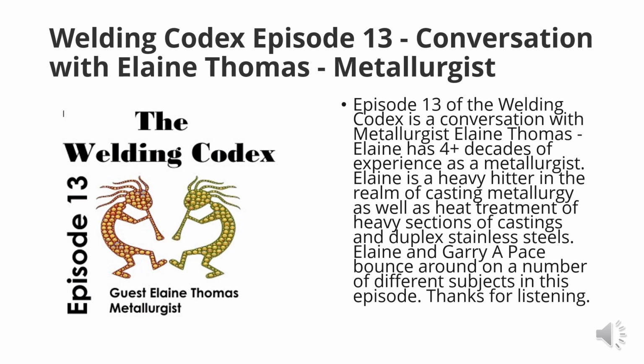I've been involved with ASTM, American Society for Testing Materials, and the specifications that deal with duplex just exploded with different alloys during the 80s. One of the ones I had a hand in helping to develop was the ASTM A890 grade 5A. That's sort of the general spec. The pressure vessel spec is ASTM A995 grade 5A. Those are called super duplexes because they're a little bit more resistant to salt water when the temperature gets a little warmer. So there ended up being duplexes, and there ended up being super duplexes.